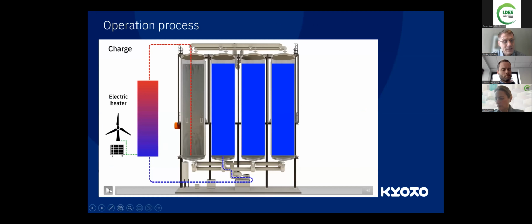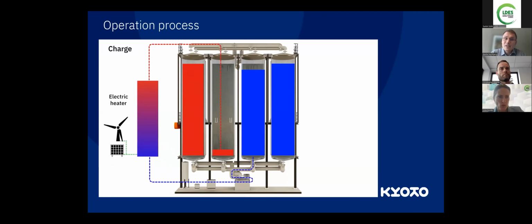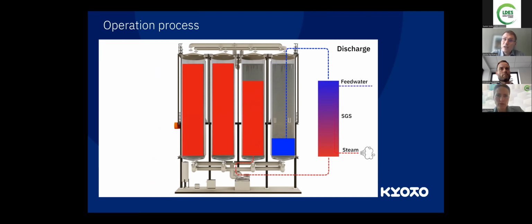As Julia said, it is a system based on molten salts. We're using a ternary salt, and basically it's a hydraulic system where you pump the liquid from the tanks. Now you see the cold tank being pumped into an electrical heater. The electrical heater heats up the salt to a high temperature, and when we want to discharge the thermal battery, we run it through a steam generator. So it is pretty simple. We charge with the electrical heater and discharge with the steam generator.